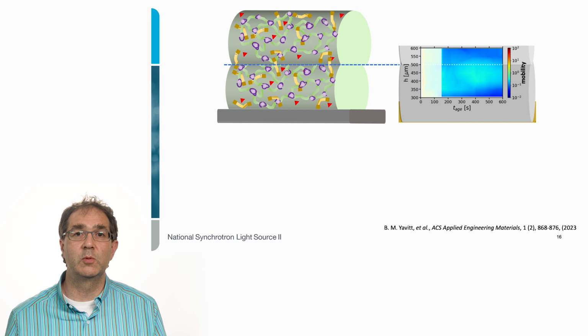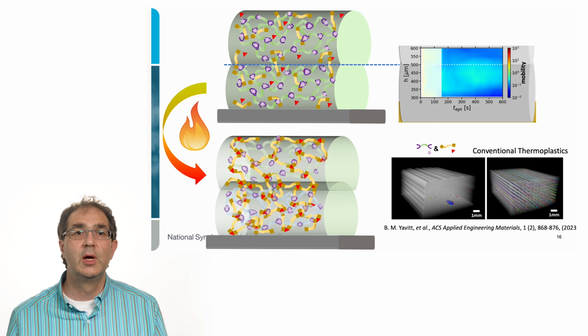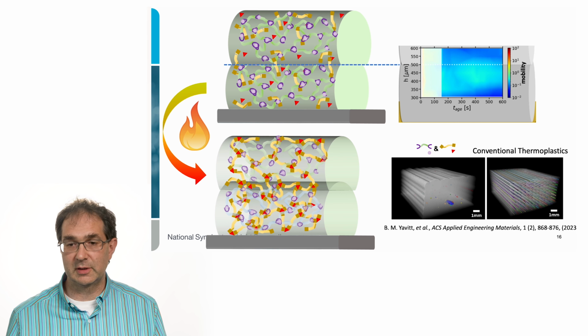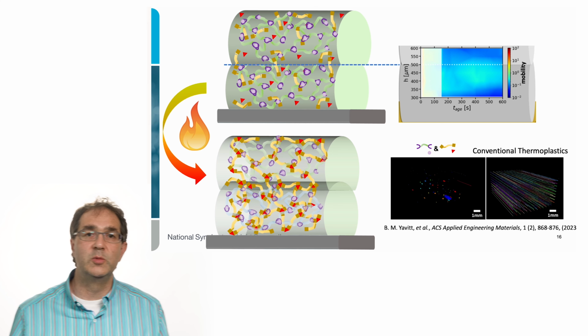And that's exactly what we wanted, going back to the schematic that I showed earlier. We are now exactly in the state where each individual filament is supported by a skeleton, but we still have the second set of molecules that is not assembled yet, which we can do by a heat treatment, and after that we end up with a solid part. And in a solid part we can't measure the mobility anymore, but we can do X-ray microscopy and look for defects in those parts. And if one does that, we see the defects like voids shown in these little colored blobs here, and it's actually easier to see if I remove the material.